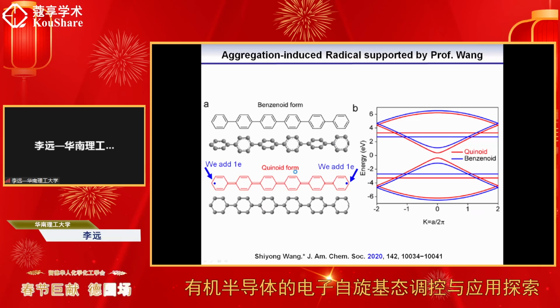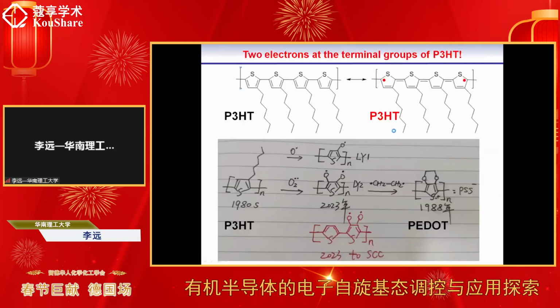So, in the beginning of my talk, I proposed that all the wide bandgap and low bandgap organic semiconductors might show diradical or multiple radical characters. However, we cannot detect the radical with the ESR spectrum. For example, the P3HT is a very famous polymer, reported around 40 years ago. And the PEDOT is also a very important polymer. Both of these two polymers have been reported for more than 30 years.